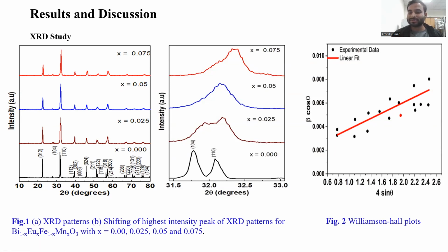With the help of the cursor, I show that this is the Williamson-Hall plot. With the help of the Williamson-Hall plot, I calculate the crystalline size, strain, and dislocation. Through the Scherrer formula also, we can calculate the crystalline size and strain. And after the Rietveld refinement, the phase change is confirmed, and crystalline size and many things we calculate about the material through the Rietveld refinement.